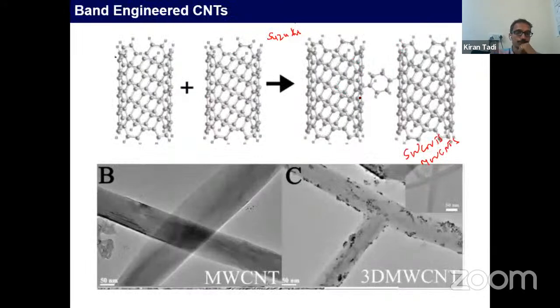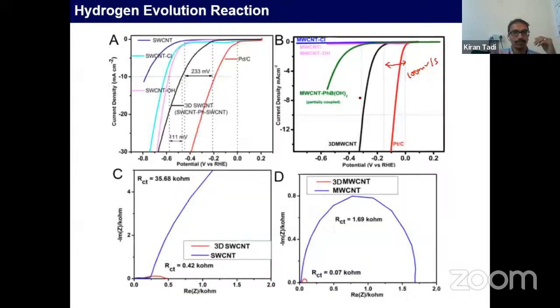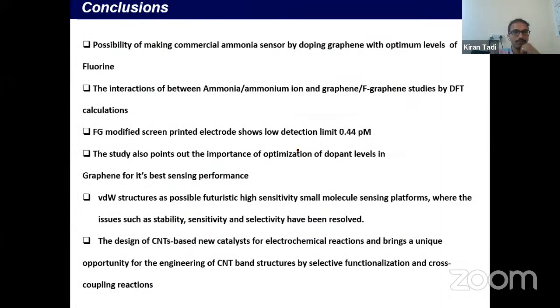So, mostly, to summarize my talk: by careful doping of graphene, we made a real-time sensor for ammonia. And in the second part of my talk, by protecting MoS2 with graphene, we fabricated a very stable, highly sensitive and selective sensor for dopamine.